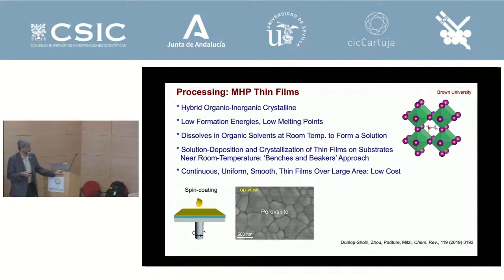For example, we do spin coating, and you can see this beautiful microstructure. It looks like a ceramic, right? Grain boundaries in aluminum oxide. If I showed this to you and said this is aluminum oxide, you would believe it, right? Or barium titanate. And then this is the cross section.